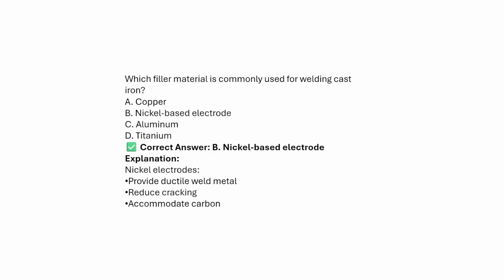Which filler metal is commonly used for welding cast iron? Copper, nickel base electrode, aluminum, titanium. The answer will be nickel base electrodes. Nickel electrodes provide a ductile weld metal, reduce the cracking, and accommodate carbon.